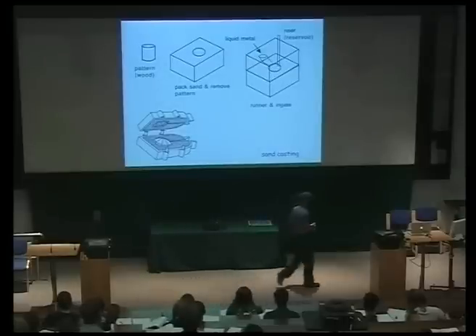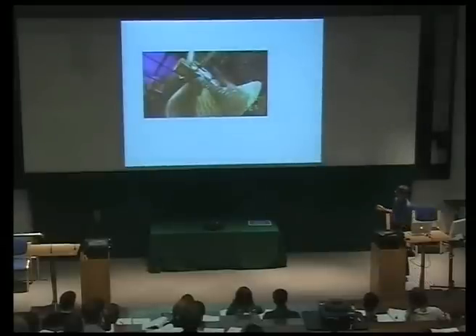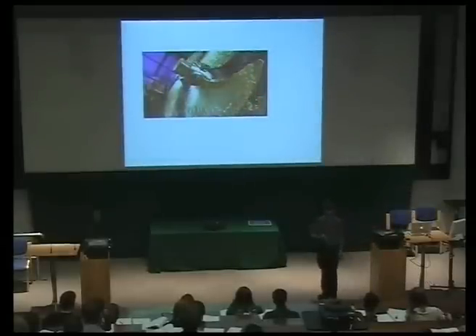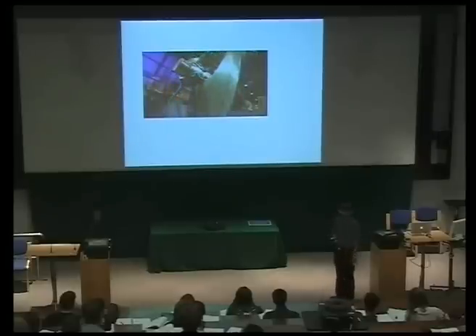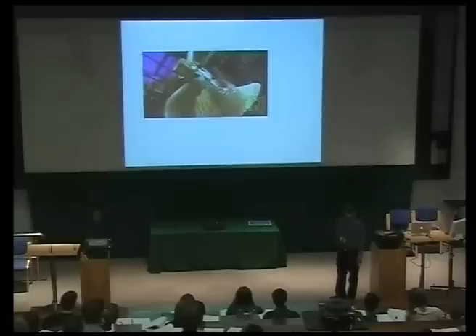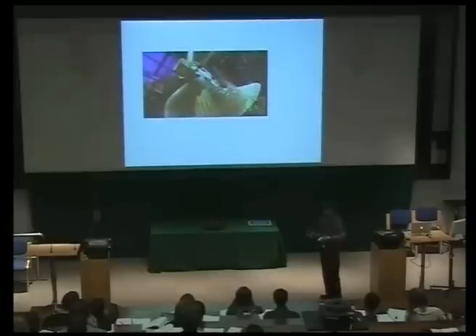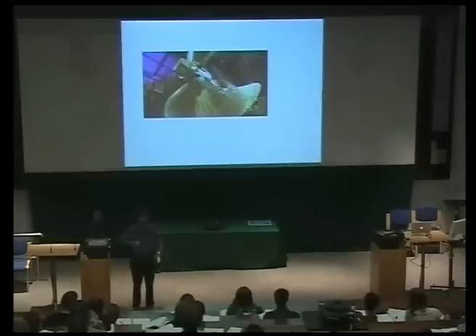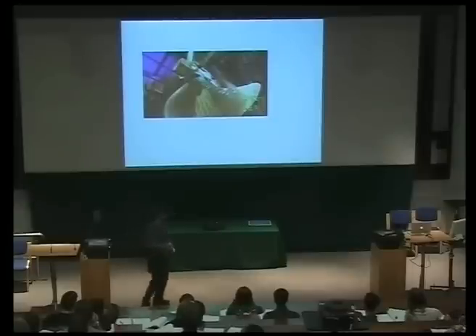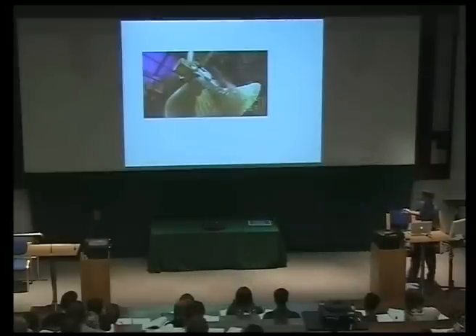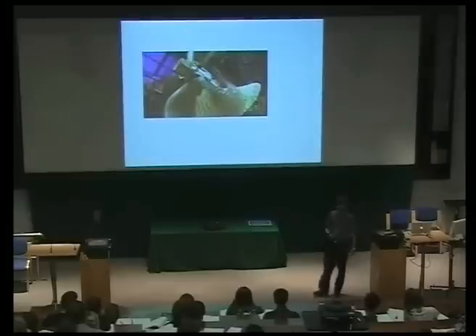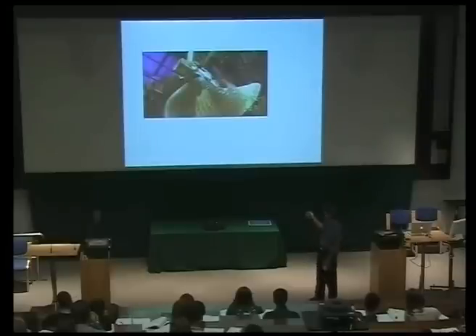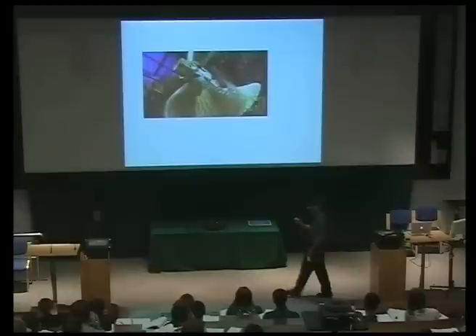So let me show you one component made by sand casting. This is a propeller for a large ship, made out of an copper-aluminium alloy known as aluminium bronze, actually made by Rolls-Royce Marine. The blades themselves are moving blades — it's not a single casting — and the reason is that nowadays you don't need a rudder; you can just change the configuration of the propeller to steer the ship. Obviously you don't make millions of propellers, so sand casting is a very good technique for something like this. In any case, the surface has to be machined into the right hydrodynamic shape afterwards, so the surface finish doesn't matter very much. Sand castings have a relatively poor surface finish compared with die castings.